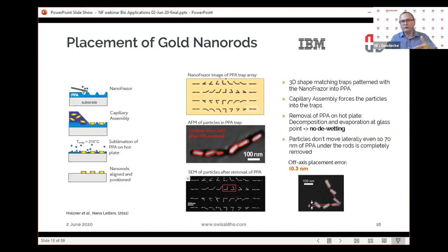And so here, what you can do and use it for bio applications, I see, is you could use little gold rods if you don't want to go into the clean room afterwards and deposit it. You can have little gold particles, position them by basically washing them over or let the coffee stain effect take over. Position each gold particle in a groove, then transfer the whole thing to a hot plate, let it heat up, everything sinks down, and you have fairly accurately positioned gold nanorods. I don't have to repeat again what you can do with those.